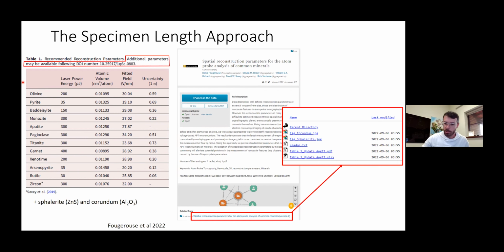So they all work pretty well with this approach. I had some issues with things like apatite, for example. You see there are no uncertainties for this mineral because it was very difficult to image them back and forth before and after analysis. I think the electron beam sometimes damaged the minerals so badly that once we put them back into the atom probe for a long run, they would basically fracture. So some minerals were very tricky like this. I tried others like iron oxide, such as goethite, which is the hydrated iron oxide. Couldn't get it to work either. So there is a limitation here: the minerals need to be resistant to electron beam microscopy, basically.